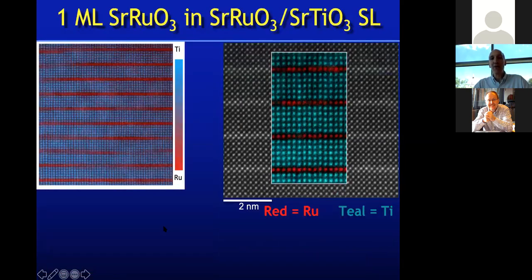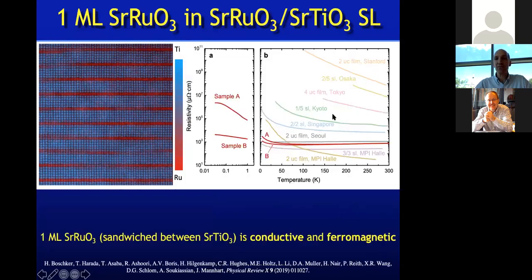Okay. Now let's look a little bit more broadly and then think about the properties that this has. So in the strontium titanate case, here's a broader TEM image. I show that again because you can see that there are some regions where, on average, we controlled our flux correctly, but there are regions where we have a little bit less than a monolayer. And there's a region here where we have a little bit more than a monolayer at that position. And let's look at the transport properties.